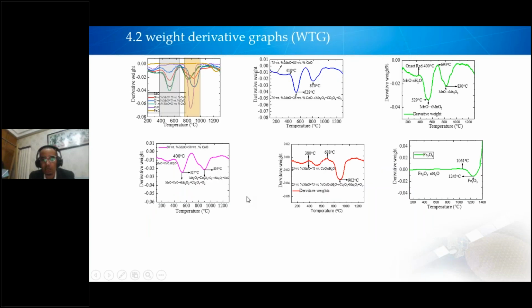Okay. The other is a weight derivative graph. When we see the weight derivative graphs, we see that phase changes happen. At what temperature do these phase changes occur? We see that most of the phase changes occur for this composition at about 400 to 500 degrees centigrade in the first case, but we don't know exactly. It has to be further tested at what temperature this is really the phase change. It needs an exact test that we'll do sometime later.